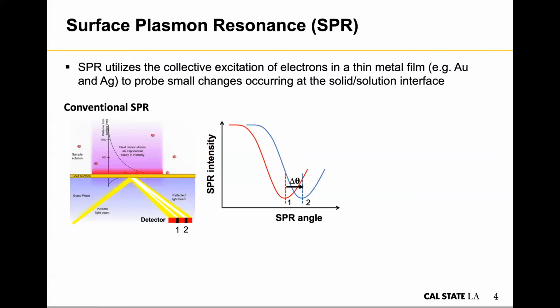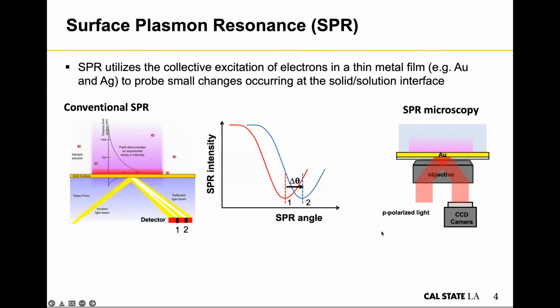Then people started to build imaging techniques based on SPR. By utilizing a prism or a high resolution objective, you can use p-polarized light and collect the images through a CCD camera. In this case, you're no longer monitoring the angle shift. Instead, you're looking at the intensity change occurring at the same SPR incident angle, so this is the delta I. You will get images, and at each pixel you're looking at the intensity change, the delta I here. Within a certain range, it is believed that the intensity change is proportional to the angle shift, which can be directly correlated to the reactions going on at the surface. So this is the difference between conventional SPR and SPR microscopy.